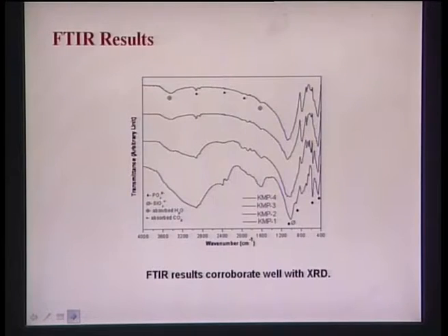Now, FTIR spectra essentially tell you that you have this pure phosphate peak in this material, and also you have some H-O-H vibration peak, which is roughly around here. So, this vibration peak tells you that this material has some hydrated phosphate phase, and this phosphate phase indicates that you have MgKPO4 also, because you have the silicate phase and you also have the MgKPO4 phase.